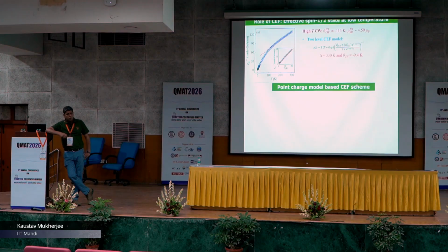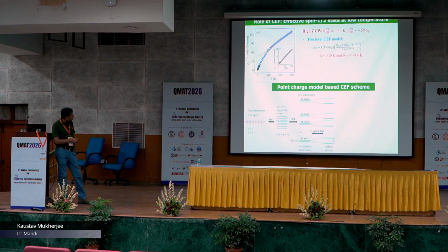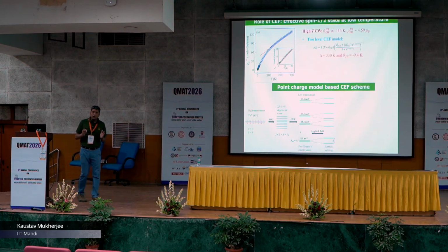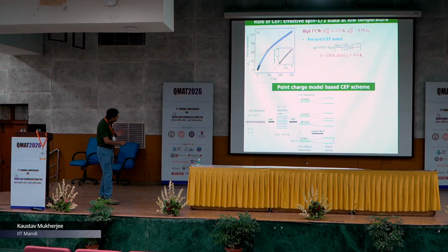But first we have to look at what the condition of Yb ions is at high temperature. Basically, this Yb ion has 13 electrons in the f shell, and using term symbol calculation we found the total spin moment S as half and L as 3. So J was calculated to be around 7/2. Under spin orbit coupling, these levels are split into 2J+1, that is 8 degenerate states.